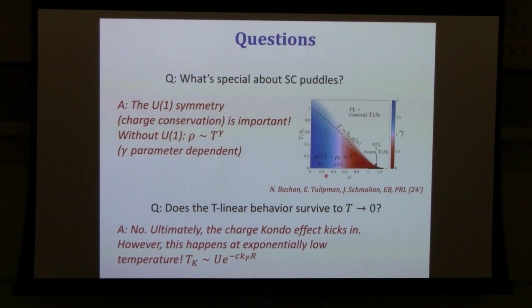Okay, and it turns out that ultimately this linear in T behavior does not extend all the way down to zero temperature. There is Kondo screening. This is a phenomenon well known from the Kondo effect. If you have a spin impurity in a metal, and it's antiferromagnetically coupled to the spins of the surrounding electrons, at low energy, it tends to form a singlet with the spins of the electrons from the Fermi sea, and it basically disappears from the low energy theory. And this actually happens here as well. The charge Kondo effect can also undergo Kondo screening.